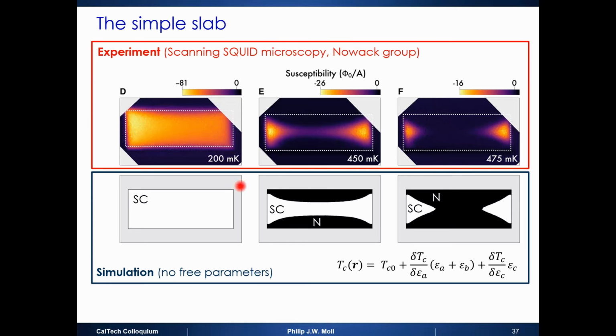But then if you go above bulk TC, so let's say at 450 millikelvin, you see superconductivity is not yet gone. It remains, right? You go to 475, it still is not yet gone. Now, all of this is well known in macroscopic crystals under uniaxial pressure. But now we have an interesting texture.